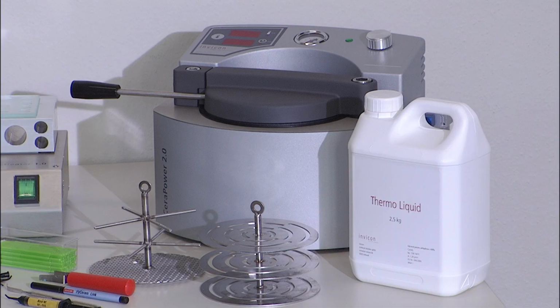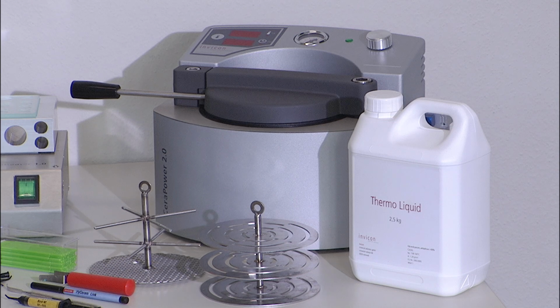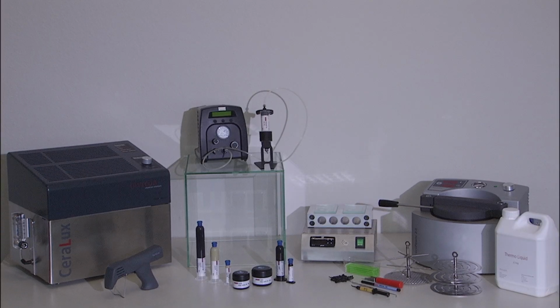And next to the preheater station, there is our CeraPower device. The CeraPower device is for curing HyCeram. HyCeram does not need a special curing technique, and therefore we have our CeraPower unit where you cure HyCeram with heat and pressure. So inside the pot we have a thermal liquid, and we cure with 120 degrees, 4 bar pressure for 60 minutes. Good, so these are our devices, first of all, just to have an overview.